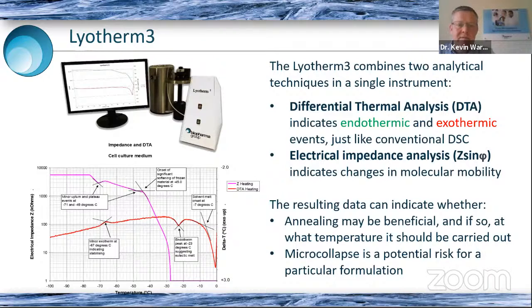And again, this is one of the first things we did when we were a very young company. Biopharma developed what we call a resistance analyzer, Lyotherm. And this was very simplistic technology. What we simply did is put our formulation into a glass vial. We inserted some resistance probes, which measured the resistance with a very low voltage AC circuit.